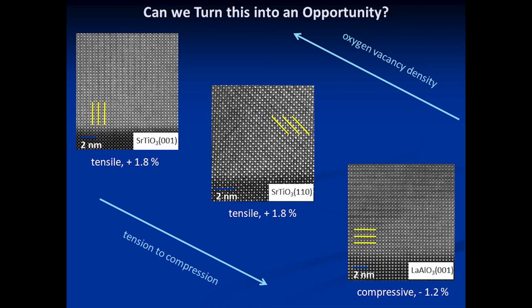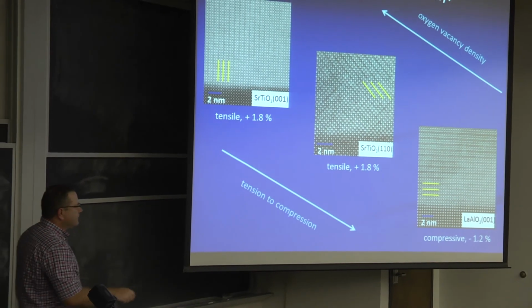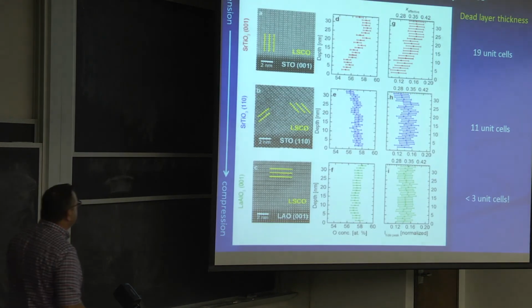We also said, well, let's flip the substrate. So instead of putting the material under tension, making it expand this way, let's compress it this way. It should have to expand out of the plane, and I should put in parallel sheets of oxygen vacancies that run parallel to the interface. And that's exactly what happened. And we knew that we had this sort of figured out, okay? So you can control how many oxygen vacancies you have, what direction they run in, exactly how they order, just by basically flipping around the substrate on the bottom, okay?